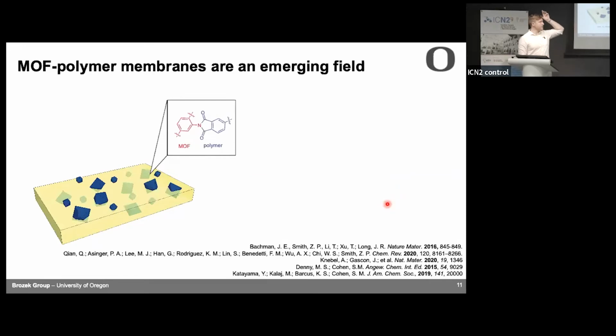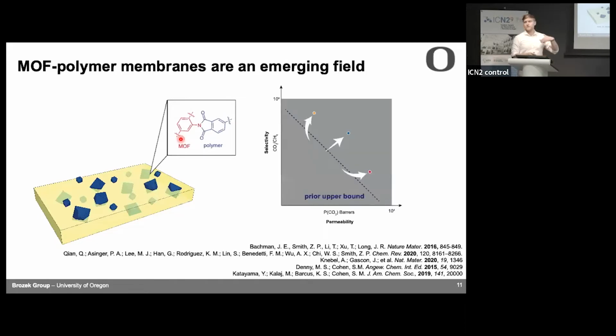In the last 15 years or so, people have become really interested in making these composite membranes where you have the polymer that you would normally use in a conventional membrane, but you embed MOF particles in there. When people were first studying this, these were particles of all different sizes. In many cases, they were actually just bulk crystals. Sometimes the MOF and the polymer are just mechanically mixed with each other. And sometimes people form actual covalent linkages between the MOF and the polymer. And when we did this, people noticed that we actually can extend the performance beyond that initial Robeson upper bound. And so now there's a goal of constantly pushing that upper bound to greater and greater performance.